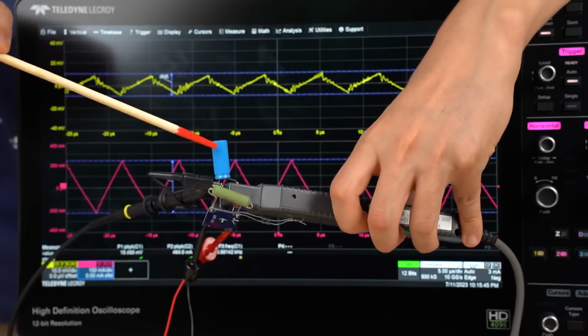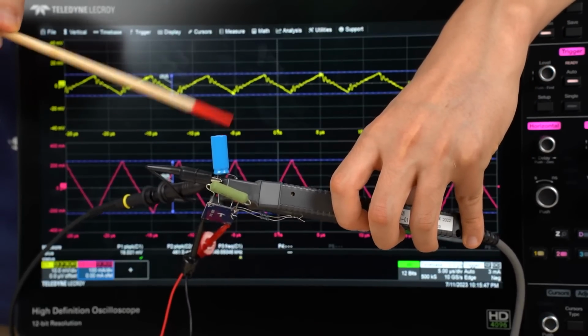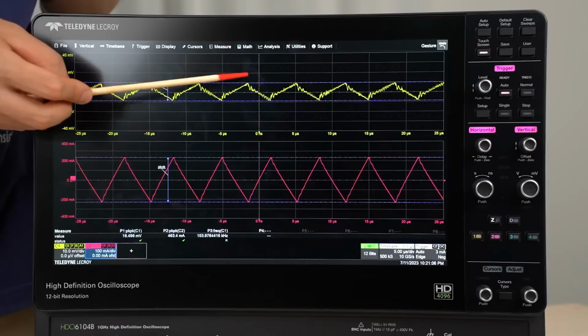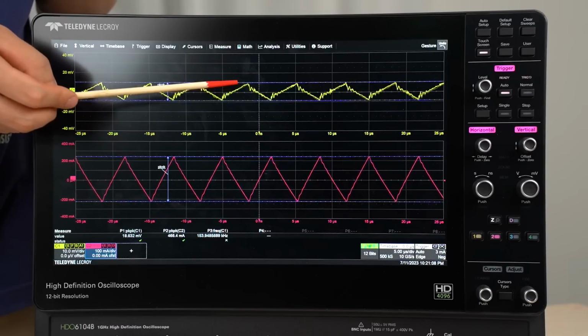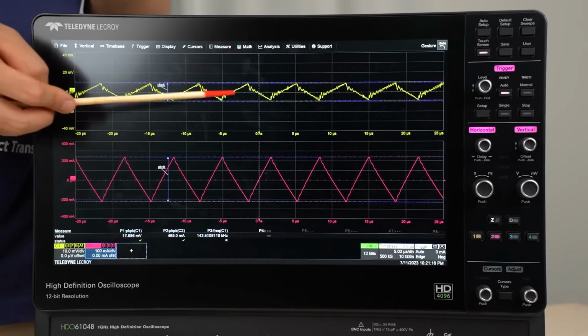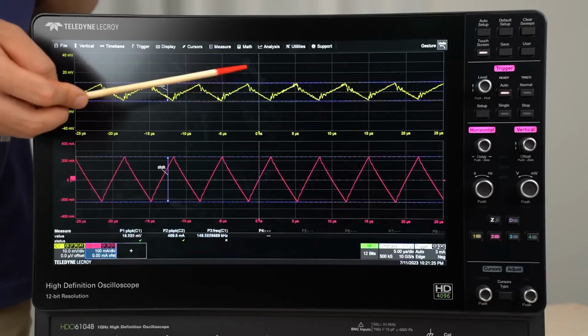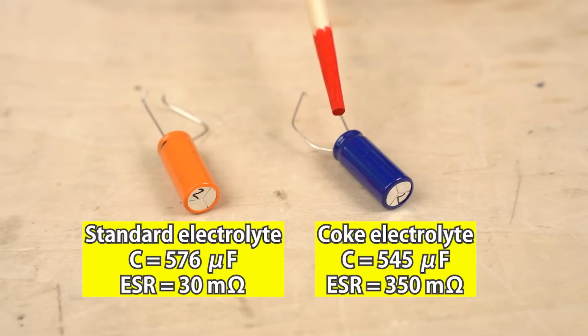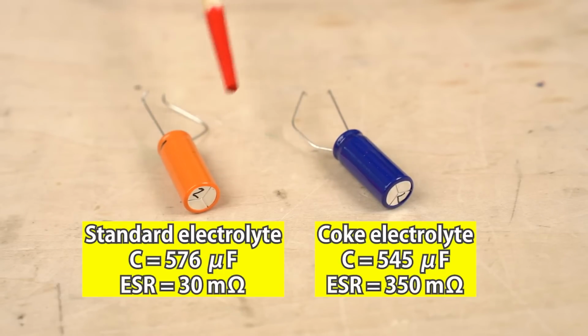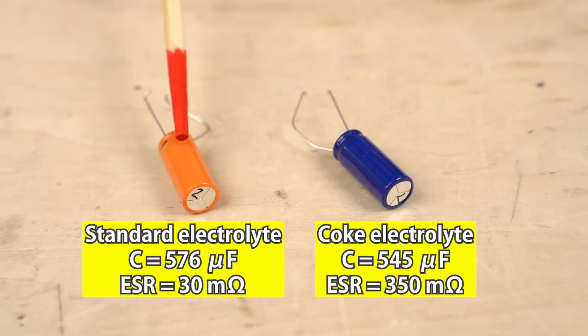My hand-winding capacitor seems pretty good. It seems to be reliable enough for practical use. The measured capacitance is 576 microfarad, and the ESR is 30 milliohm. You can see those characteristics from the waveform as well. Next, I'm going to test the capacitors whose elements were wound mechanically. Same elements, but different electrolyte. The orange one has standard electrolyte in it. The blue one has Coke in it as electrolyte.